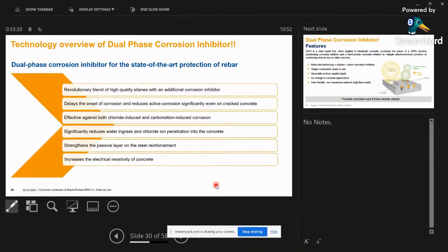So what's the difference? How does it work? There are different types of surface applied corrosion inhibitors, but what we are talking about is a silane based dual corrosion inhibitor, deeply penetrative in nature, because it has very high quality silanes. Silane is the smallest molecular structure in the chemical chain of the impregnators. Of all the impregnators which are possible, the lowest molecular size is that of a silane.